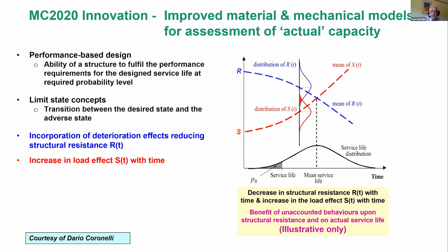resistance and load effects, and on the horizontal axis that's time. And you can see the blue line is the resistance curve, which is shown deteriorating with time, and the red line is the load effect increasing with time. So that might be physical load, but it might also be environmental load. And as those two curves increasingly overlap with time, you end up with a basis for establishing service life.